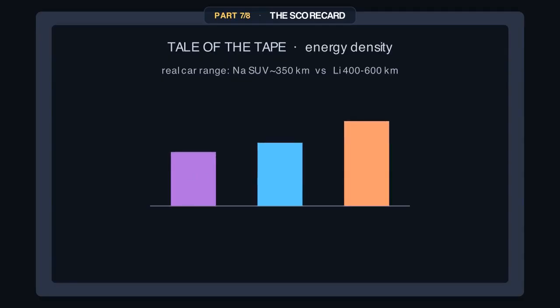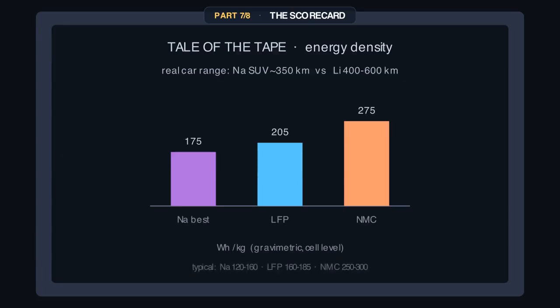Gravimetric energy. The single best sodium cell, Naxtra, hits 175 watt-hours per kilogram, near LFP, but that's the best. Typical sodium is only 120 to 160. LFP reaches up to about 205, typically 160 to 185. NMC is 250 to 300. Volumetric, sodium's lower too. In a real car, that's a sodium SUV going maybe 350 kilometers, where a lithium one does 400 to 600. On energy density, sodium loses. Full stop. Power tells a similar story with a twist.